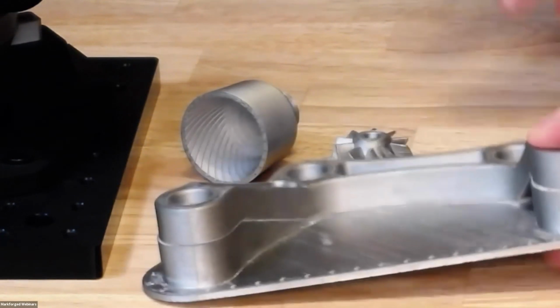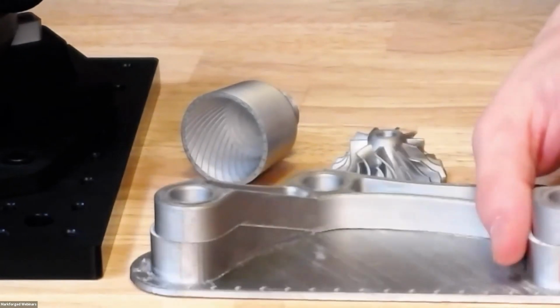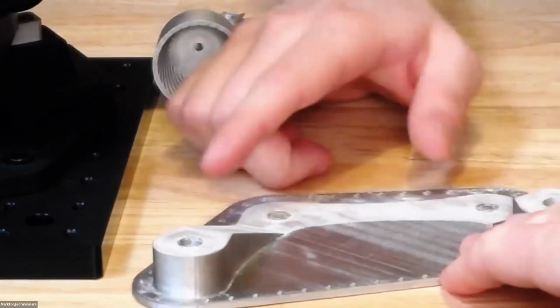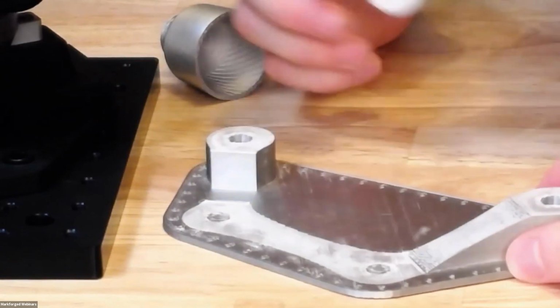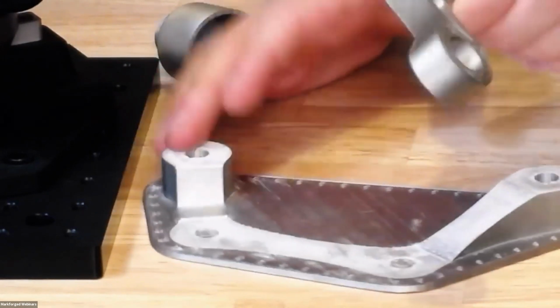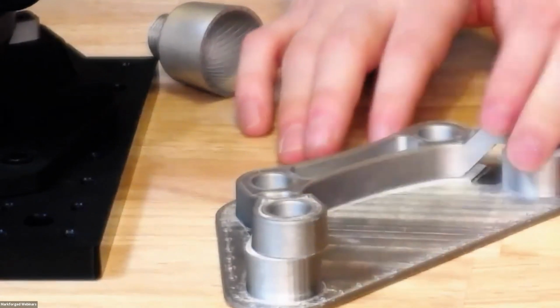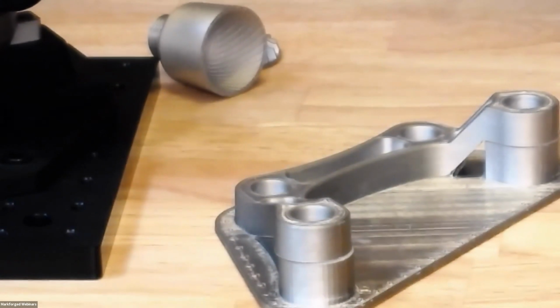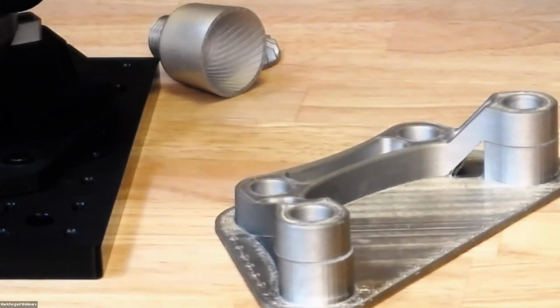The supports are like materials. This is also steel here. What is not here anymore is an interface layer. So normally on top of this raft here and below this printed part here, just get in frame, you would see basically a small ceramic release layer printed. And as you sinter, that release layer turns from a filament to a dust, and you just break it apart after sintering.